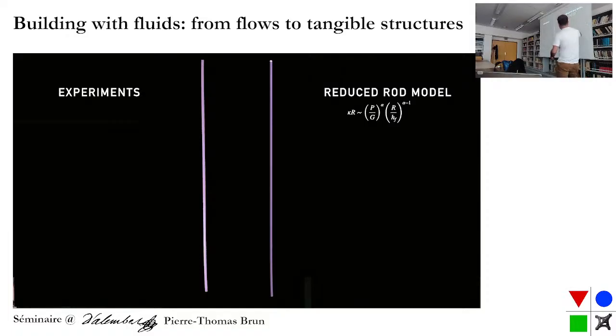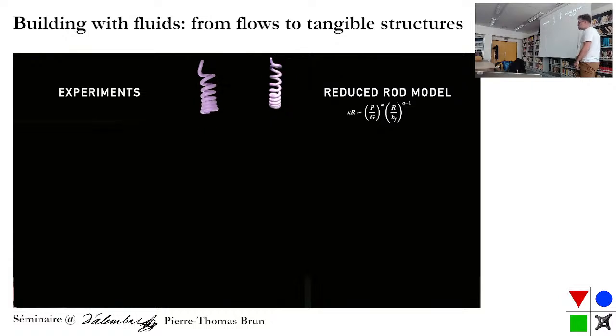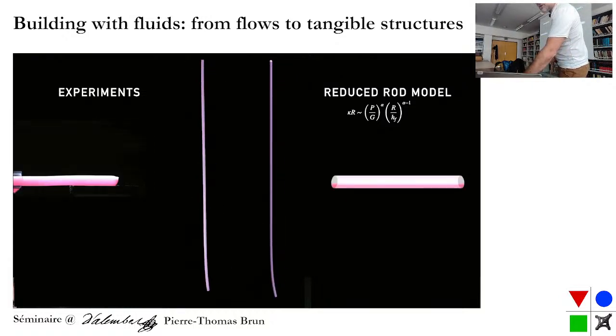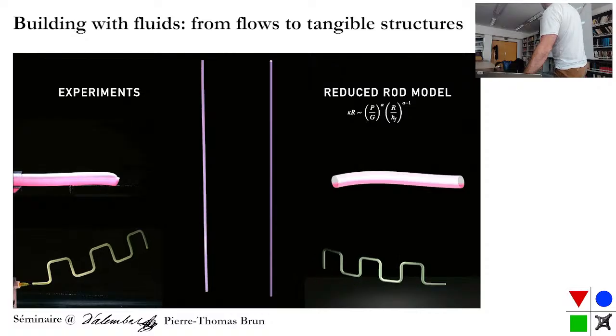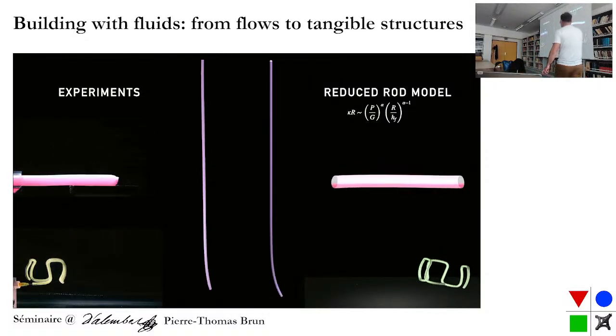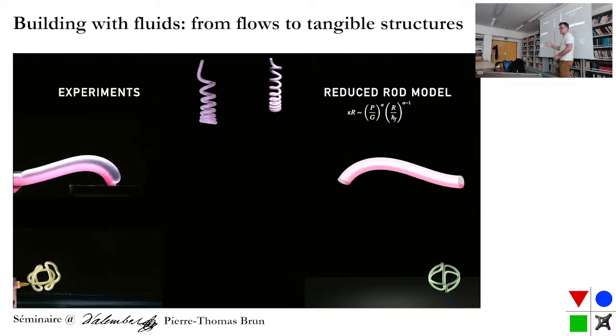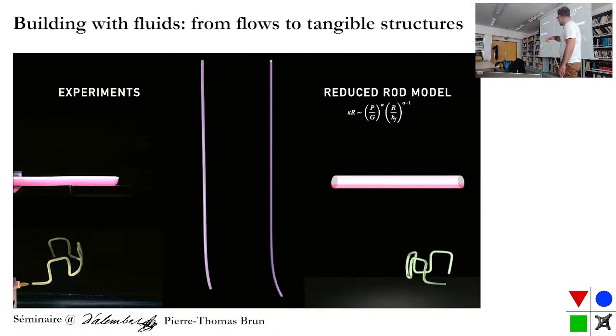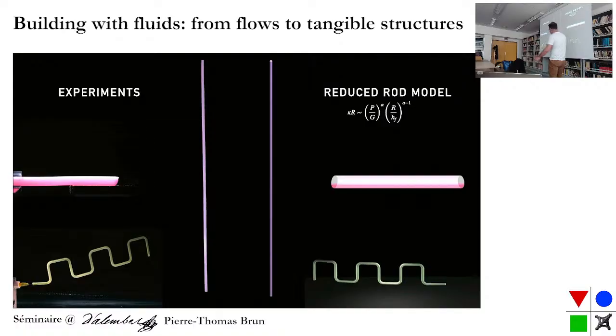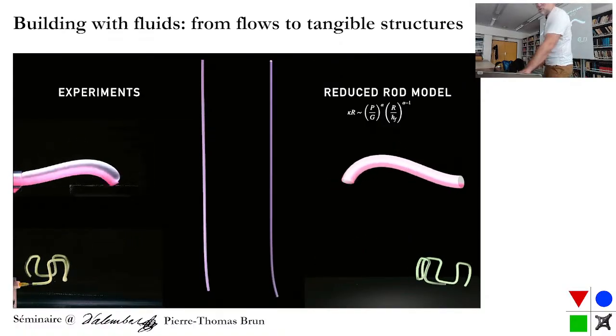You can test whether this formula is correct or not. So here we have a long hair, and that's about 40 centimeters or so, and you inflate it, so gravity matters in this case. So as it curves, it will curve more at the bottom than at the top, and as you increase the pressure, you increase the natural curvature if you want, and so you can integrate the Kirchhoff equations for elastic rods, and things are working well. Do the same in contact with something, you can do the same. That's inside water, so to suppress gravity. So if you have uniform curvature, essentially you're living on a sphere. And so if you have any random shape, you will form a small sphere that will close.